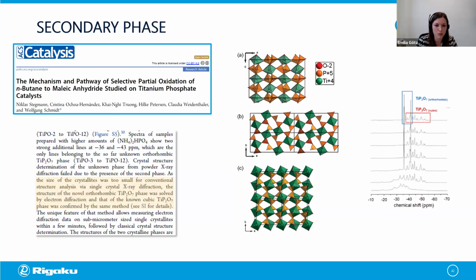And they tried XRPD first, but because of the presence of the other polymorph, they weren't able to identify the correct structure of the unknown polymorph. And then again, for a single crystal X-ray diffraction, the crystals were too small, which led them to 3D-ED, which worked really nicely to solve the structure of the unknown polymorph.